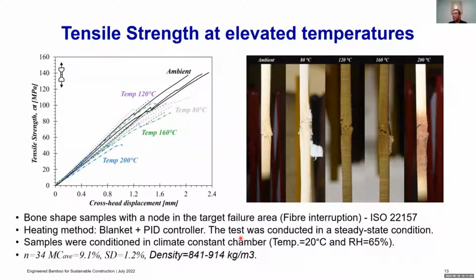But we very quickly realized that if we wanted to understand fire performance and if we wanted to do tests at a larger scale, round bamboo was not going to have a very high resistance. So we decided to focus more on laminated bamboo. But what you see here is that there weren't any changes in the failure modes, but there was definitely a significant reduction in the strength of the material.